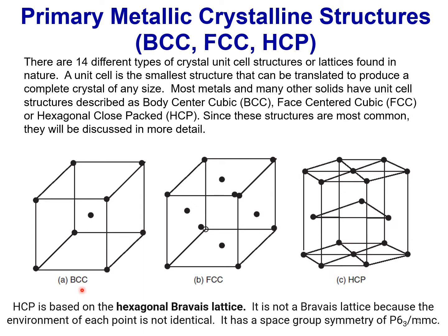So low alloy steels, the material that makes up feeders, as an example, and pressure tubing in light water reactors, is primarily body-centered cubic, although even in the FCC steels there may be a little bit of BCC, because it's a multi-phase, multi-precipitate kind of structure, often different engineering alloys. So I omitted to say that. In the BCC case, feeders are low alloy steels, which are BCC. End fittings are a ferritic martensitic steel. A ferritic typically is BCC as well.